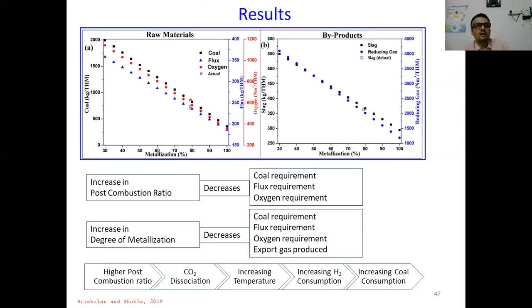Now I'm going to the results. The result of the static control model is that, if you look at this graph, these are the variations of coal, flux, and oxygen for different levels of metallization in the pre-reduction chamber. As metallization increases, the requirement of coal decreases, which is very much obvious. So an increase in the post-combustion ratio decreases coal requirement, flux requirement, and oxygen requirement, and an increase in metallization decreases the coal requirement, flux requirement, oxygen requirement, and export gas produced. These are all well-known effects, but how much quantity they will take, for that we required a model framework and we have developed it.